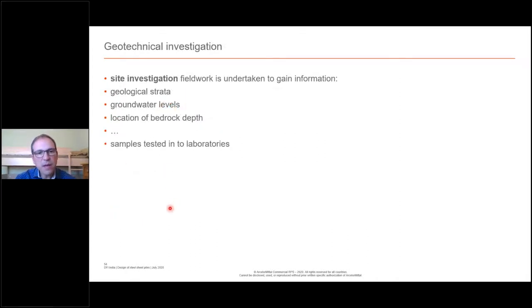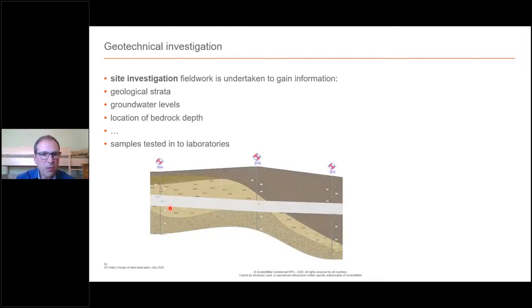But very important, I think, and I would like to emphasize on that, is the geotechnical investigation. The site investigation will have a big influence on the optimization factors, because if you have a very good knowledge about the soil properties, about the stratification, about the levels of the water, then you can really optimize. If you don't have this type of information, like here, for instance, where you have only three or four borings and you have to interpolate in between, you might have to be more careful about the selection of the parameters and the position of the layers, because as you see, they can vary.